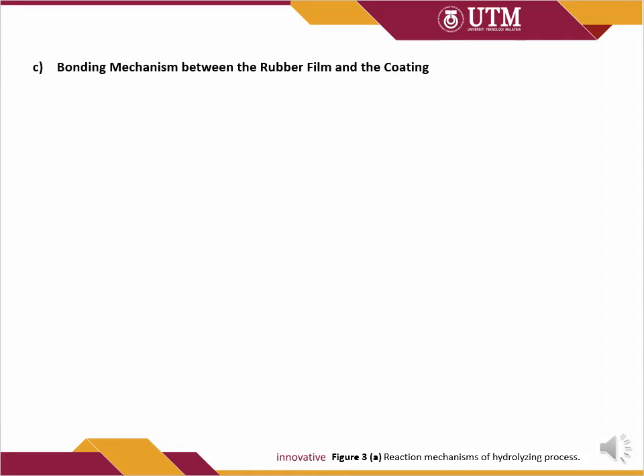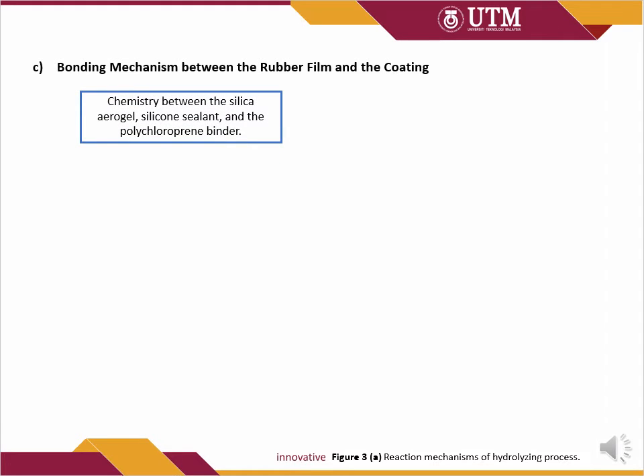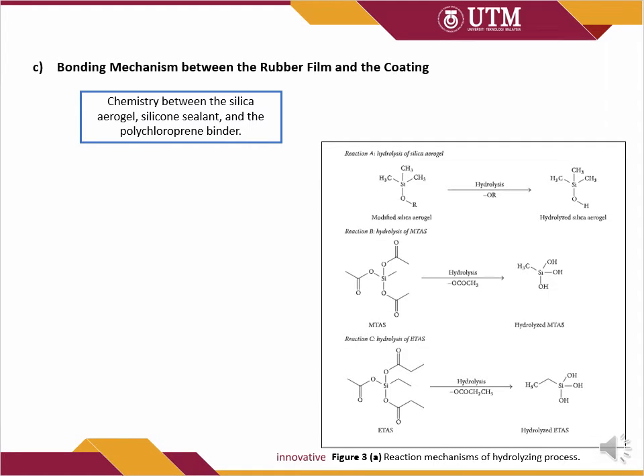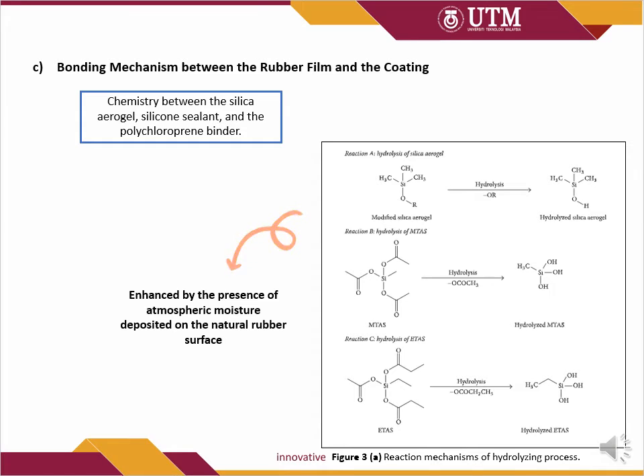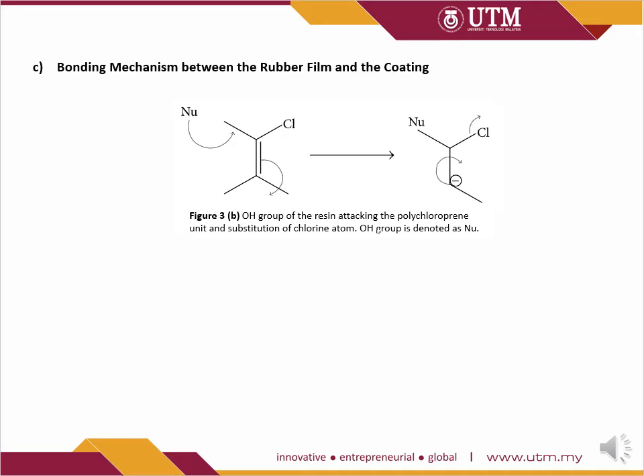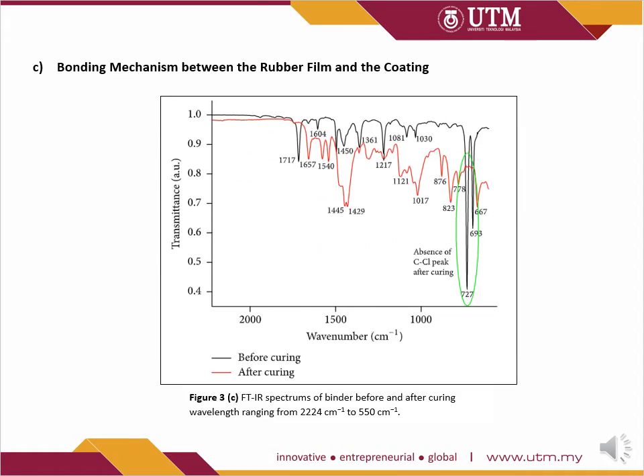The mechanism of the interaction between the nanocoating and the rubber film can be understood by referring to the chemistry between the silica aerogel, silicone sealant, and the polychloroprene binder. Figure 3a shows the coupling agents in silicone sealant and the silica aerogel are converted into their hydrolyzed state. This process is enhanced by the presence of atmospheric moisture deposited on the natural rubber surface. Hydroxy group of phenol formaldehyde interacts with carbon-chlorine group of polychloroprene, forming a chemical bond with two matrices as shown in figure 3b. Peak due to the carbon-chlorine stretching frequency has disappeared after curing as shown in figure 3c.